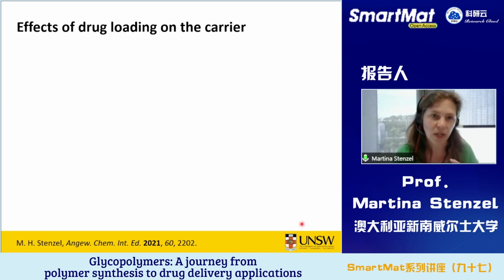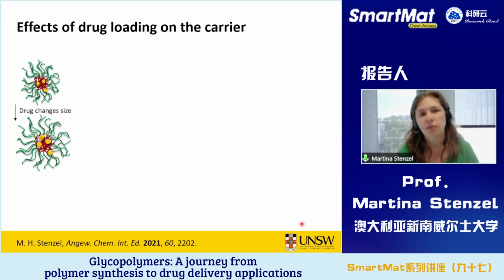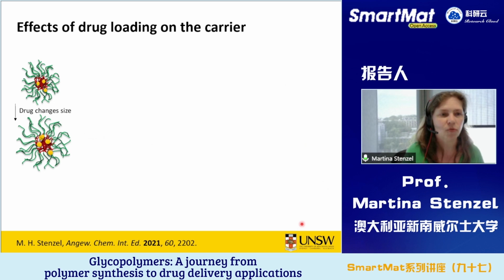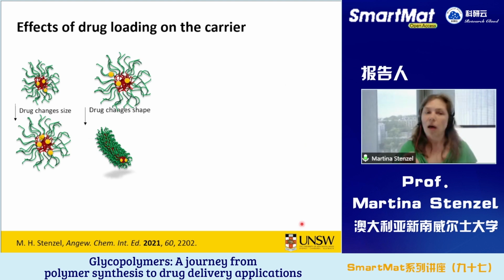So we've done many studies in this field, and there's just a summary I would like to show you. What we, for example, found is very often when you put drugs inside the particles, the drug changes the size of the nanoparticles. This is very often not a big problem, that the nanoparticles might change, let's say, from 50 to 70 nanometers. Does not have a huge influence. However, drug can also change the shape of these nanoparticles. So you can suddenly go, for example, from a round particle to a non-spherical one, or the other way around, if you increase the amount of drug.